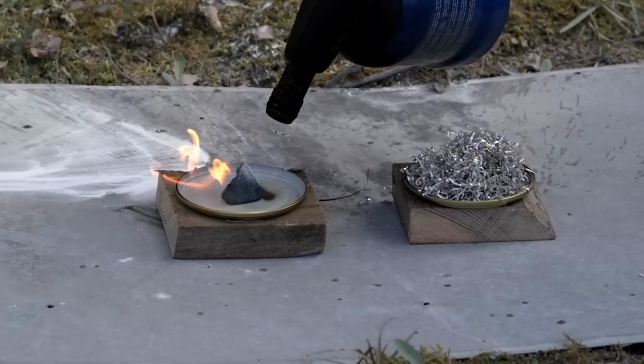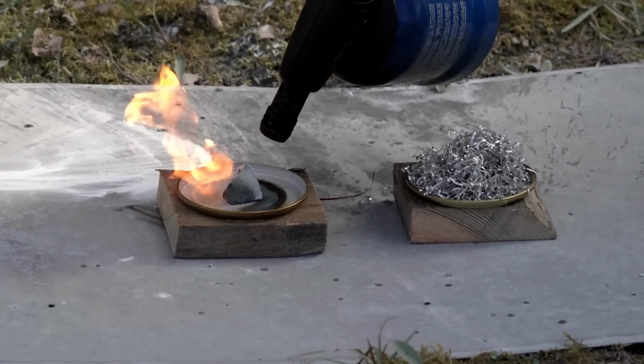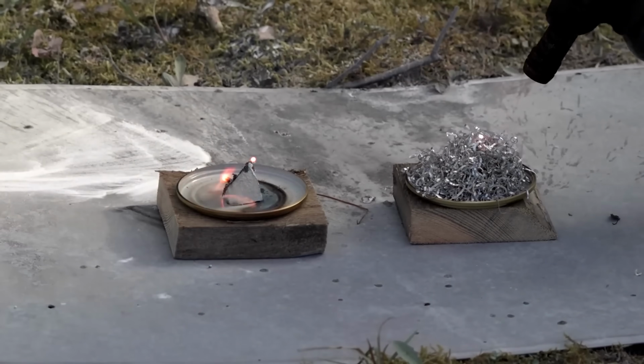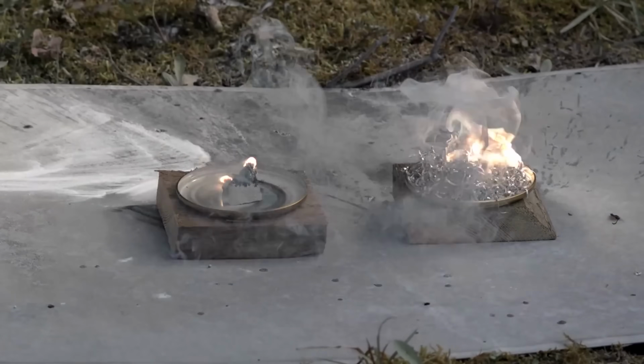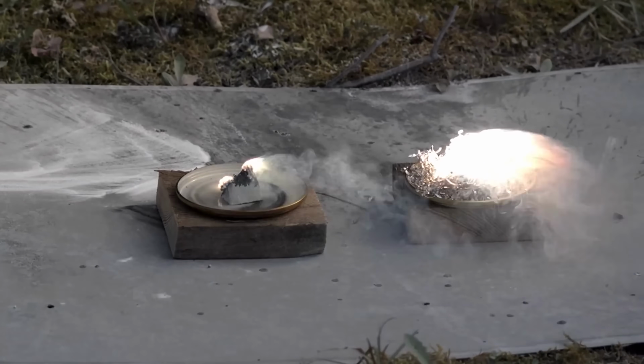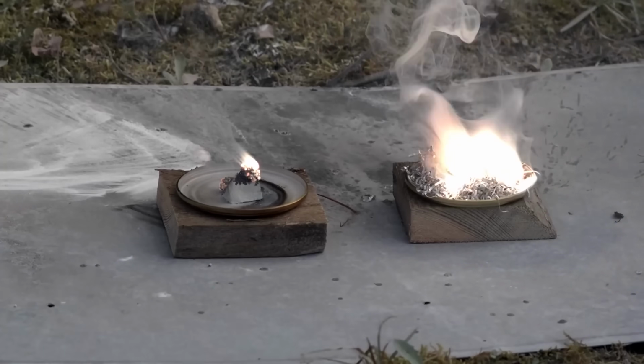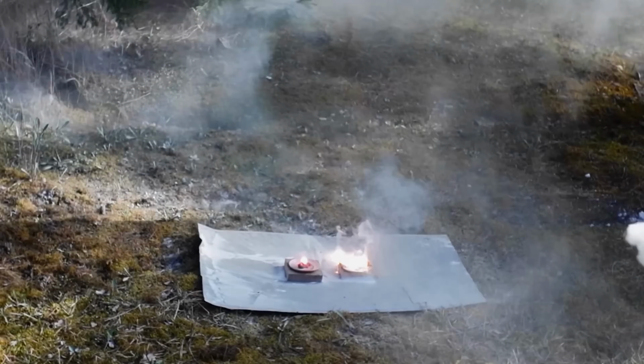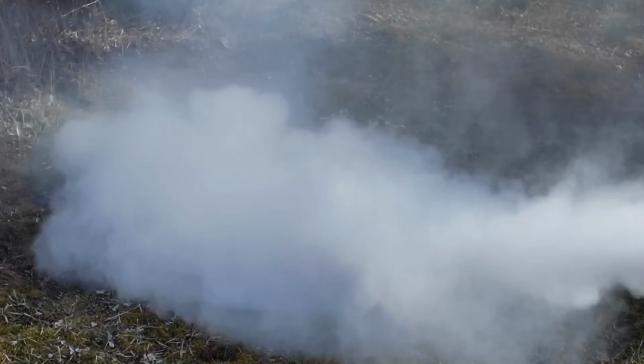Okay, let's check if less active lithium and magnesium will react with ABC powder. First, I set these two metals on fire and used the same dry powder extinguisher as the previous test. But even in these conditions, ABC powder intensifies the combustion. In some cases, the metals even release a bunch of burning sparks that make the fire even more dangerous.